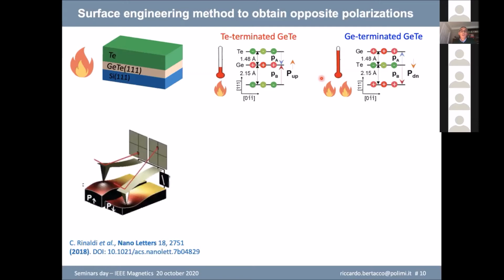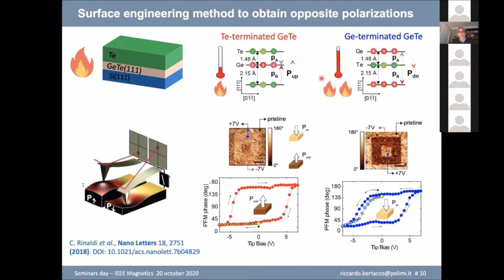And by PFM, we check that the pristine state, say the average state of the ferroelectric polarization, which is the result of this treatment for the sample preparation, is different in the two cases. So in case of tellurium terminated, it's outwards. In case of germanium terminated, it's inwards. This is a sketch of, I'll say, a summary of PFM measurements carried out. And in this color code, when you have this dark brown, this means that the polarization is outwards. With this other color, with white brown, you have the polarization pointing inwards.